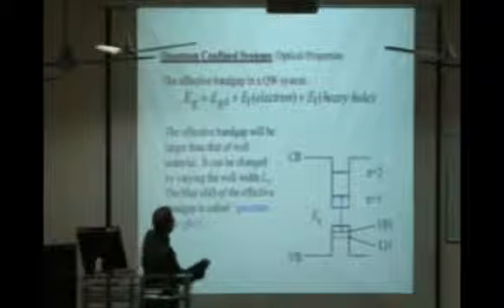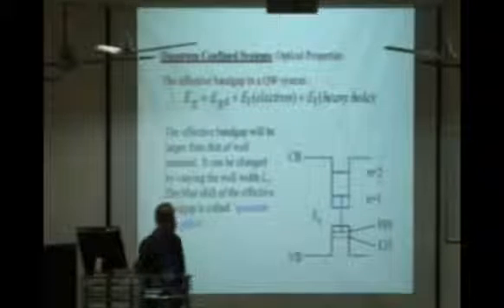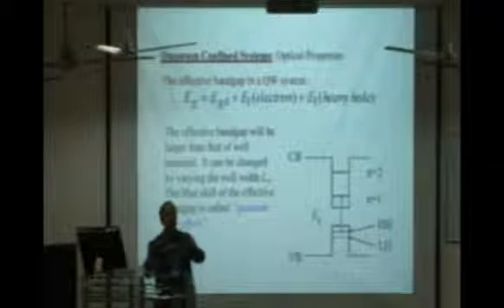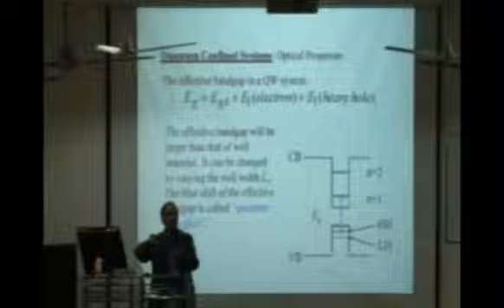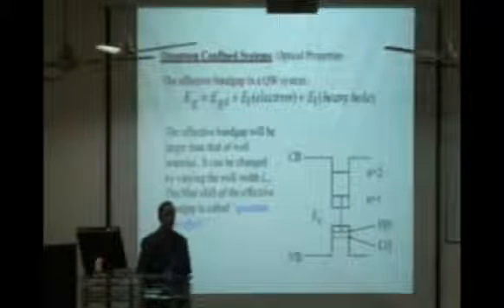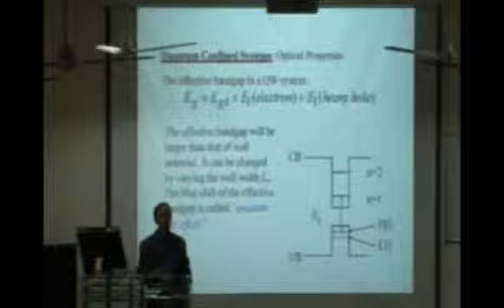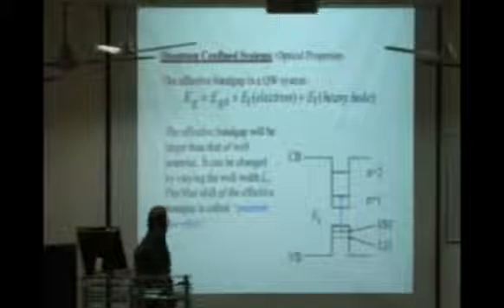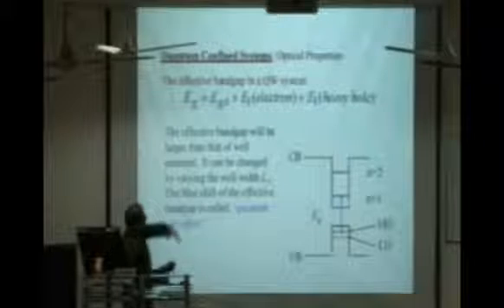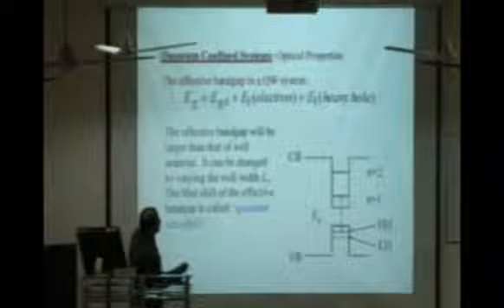And if you have a very high barrier, you can confine not only the ground state but some of the other states also. In fact, this is also a challenge. It is not very easy to get a combination of a low band gap semiconductor with a high band gap semiconductor so that you get a very high barrier height and confine many energy levels. Theoretically it is possible, but experimentally it is very difficult because of the growth problems of semiconductors with different lattice mismatch. But anyway, what we can say about this quantum size effect is that as we reduce the size, it goes as 1 over L squared, and the spacing increases. So basically you can tune the band gap of the material.